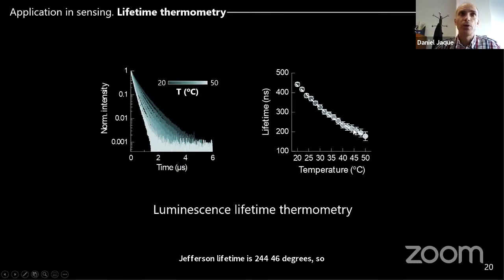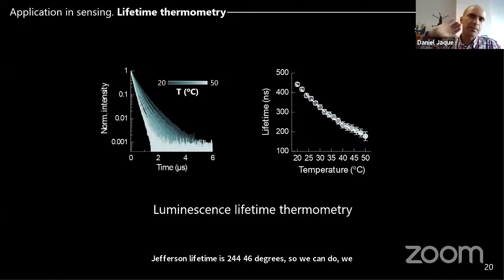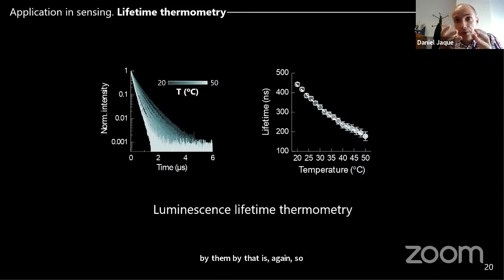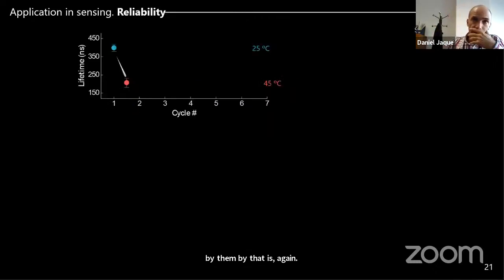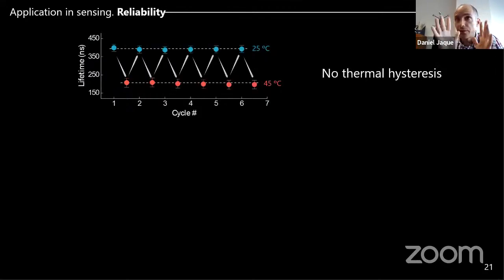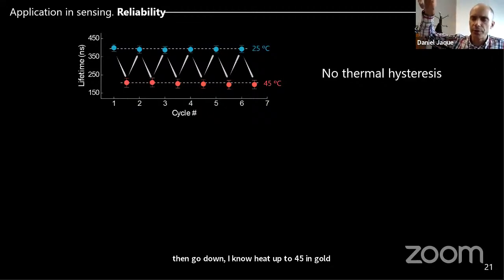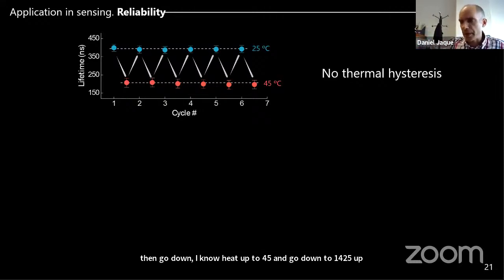So we can do what we call luminescent lifetime thermometry. It's much better than using the emission spectra to determine the temperature, because the emission spectra is affected by the tissues, okay? So these nanoparticles that are much brighter because we use sonication and we clean the surface are good for lifetime measurement. In fact, they are quite robust. There is no thermal hysteresis. I mean, you can have one nanoparticle heat up to 25 degrees, then go down, heat up to 45, then go down to 40, 25, up, down, up, down with the temperature, and you always obtain the same lifetime values.